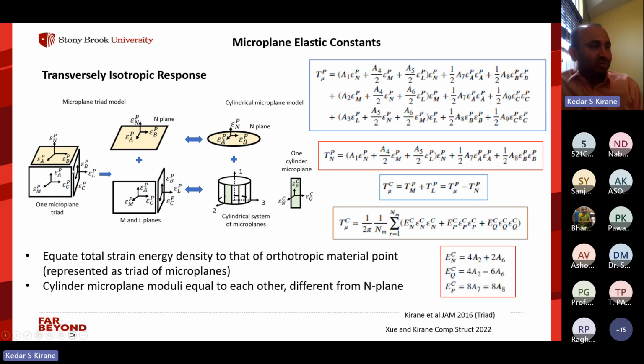So in the cylindrical model, which we recently developed, we basically adapted this concept. So the transverse plane of the cylinder is similar to one of these planes of this triad. And then the rest of the cylindrical microplanes are equivalent to the remaining two planes of this triad. So using this, and I'm probably going to skip all these equations because in presentations, anyway, it is a little hard to grasp all these equations. But these A1, A4, A5, A7, all these constants are basically related to the elastic properties of the lamina. And these are all the strain vectors, epsilon n, epsilon m, and so on.